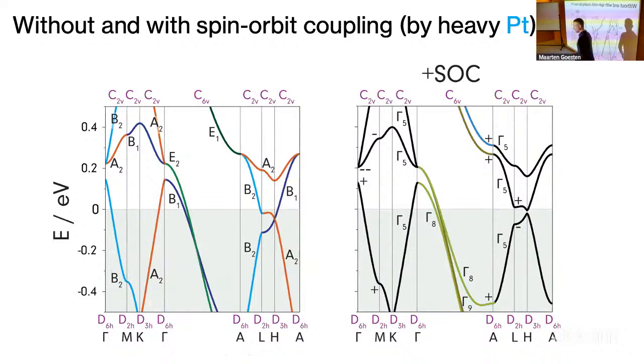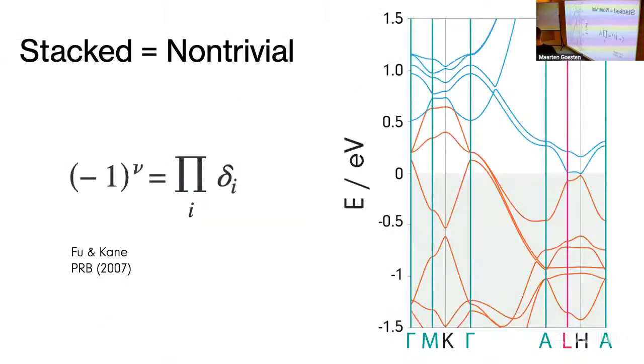These are the irreducible representations computed at the scalar relativistic level and the full relativistic level. This is the analysis that you perform to see if your material is topologically non-trivial. What you get here is that these two bands can cross at the scalar relativistic level, but when we introduce double groups, from representation theory we describe these as spin-full representations, then we see that a small gap opens up here. To determine whether the material is topologically trivial or non-trivial, you define one global set of occupied bands, those in orange, which must be gapped. Only with spin-orbit coupling do these become distinct sets, and then there is one global set of unoccupied bands.